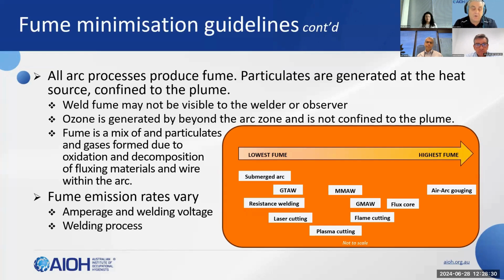Now, the composition of the weld fume generation is mainly dependent on the composition of the consumable itself, which includes the fluxes if present, and any coating the welder is welding through. Consumables for carbon steel will emit oxides of iron and manganese primarily, but alloyed wire may contain additions of chrome, nickel, and molybdenum in particular. Hard-facing consumables may contain additions of tungsten, cobalt, and high levels of chrome.